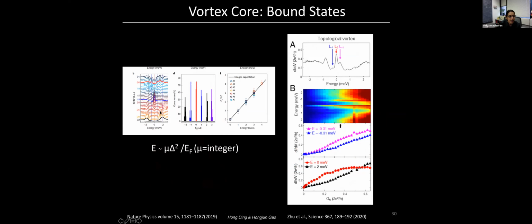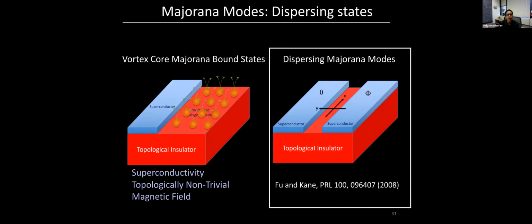unlike the trivial Caroli-de Gennes-Matricon states, you can have vortices where you have integer spacing between the vortex bound states, and this is consistent with this being Majorana fermions. Another thing they showed is that the dI/dV saturates to a value of e squared over h only for these zero bias states and not for the trivial states. And so all of this together suggests pretty strongly that these zero bias states seen in FeSeTe are in fact Majorana modes.